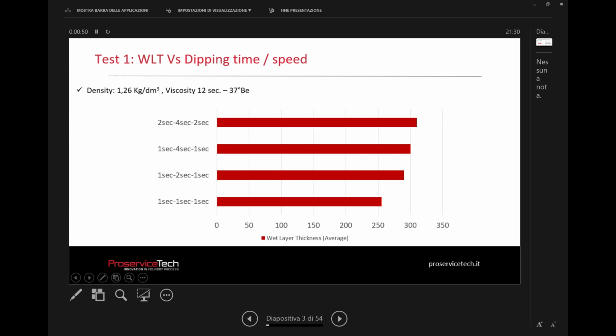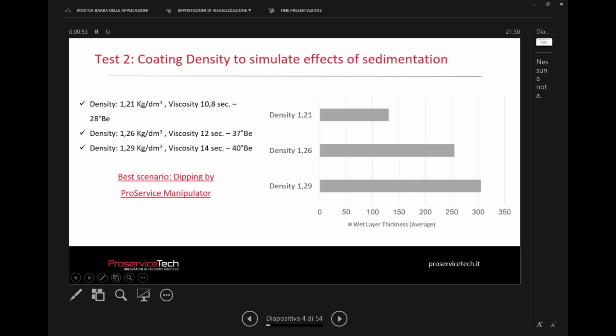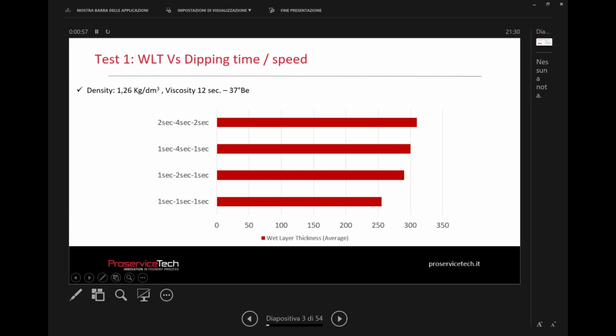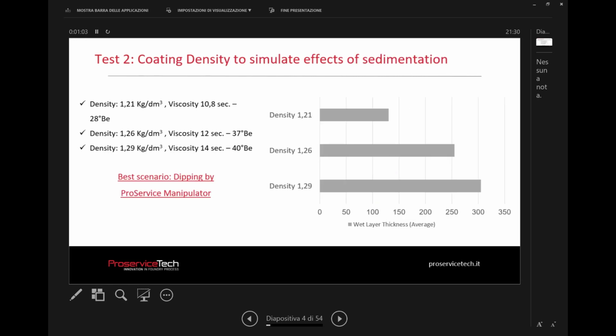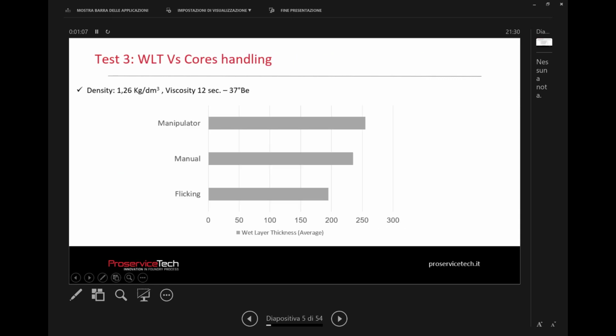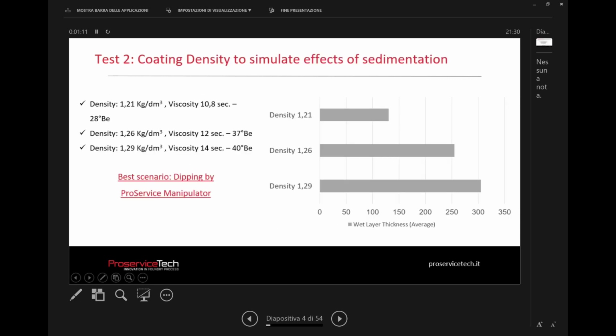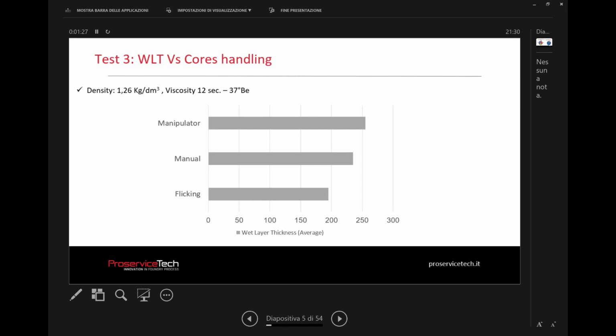As you can see, the descending and the ascending time is not so important. What is important clearly is the time that you stay inside the coating. Another thing is the effect of the density on the wet layer thickness. So if the density is 1.21, 1.26 or 1.29, the effect clearly is very, very strong, as we expected. This is very important because the sedimentation inside a dip tank produces exactly this effect. Okay, so this is measurement of wet layer thickness using manipulator manual, or for example the flicking.